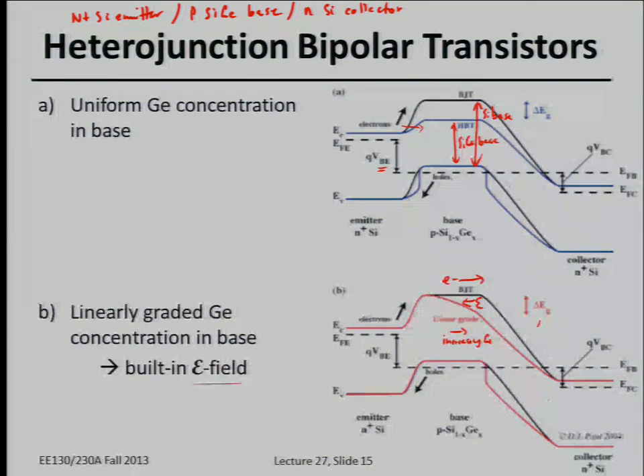Okay? All right, so qualitatively, you just need to know that with a smaller band gap base material, it turns out for the silicon germanium material system, all of that difference in the band gap actually shows up in the valence band only, right? So the key is that you see a difference in valence band energy between silicon and silicon germanium. There's really negligible conduction band energy difference between silicon and silicon germanium. Okay, so this is why it only works for NPN BJTs.